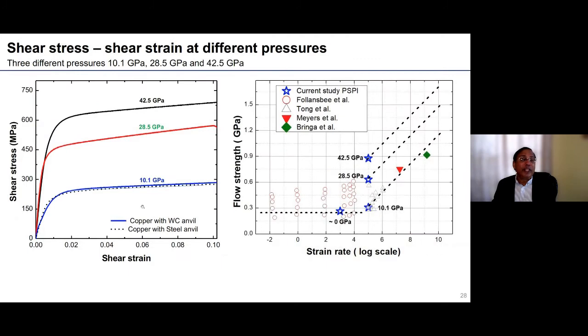Now, we can plot the same thing for the response at different pressures. Then what you see is a substantial increase in the shear stress, the flow stress, as a function of pressure. So there's a considerable increase. We go from about 260 to about 630 MPa. So we can plot this now.